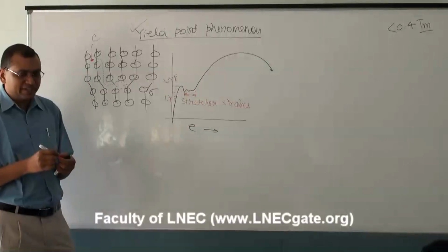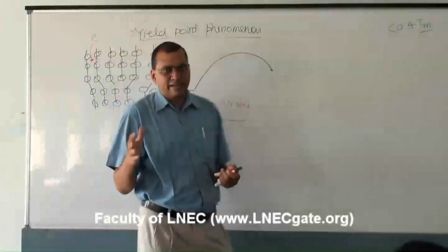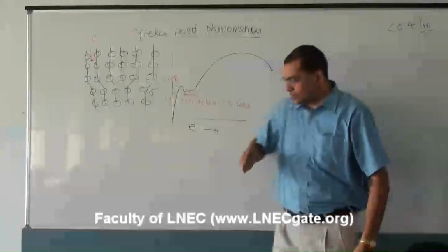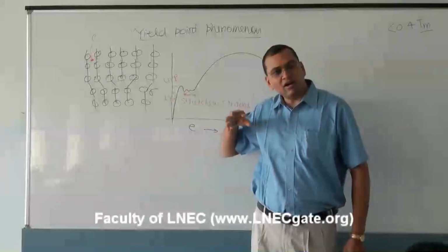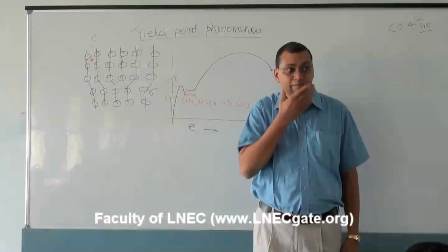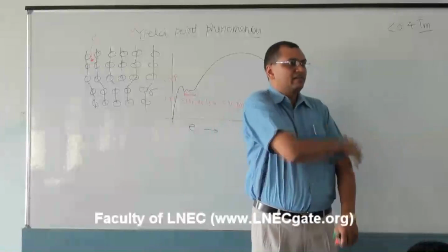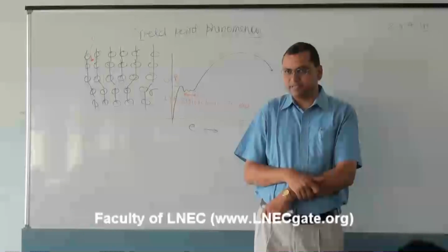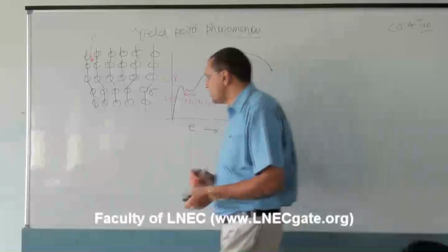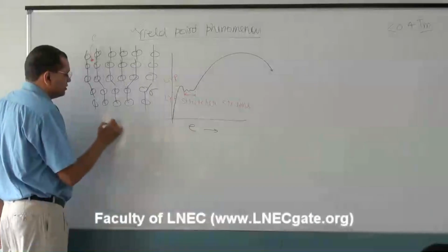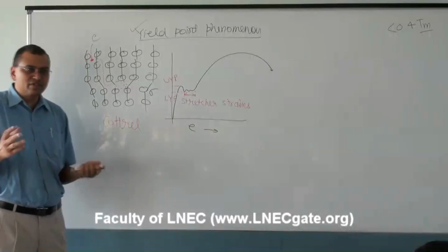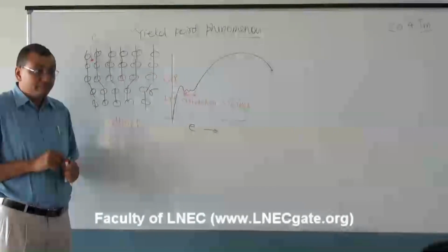Because of the edge dislocation, as we discussed, there will be a line. Suppose one atom is on this wall, another atom is on the other wall, and there is a whole plane. And all along this line there will be an interstitial void, which is larger in size along the line. So many carbon atoms can fit in on the edge dislocation site, producing a carbon or nitrogen rich atmosphere called Cottrell atmosphere.